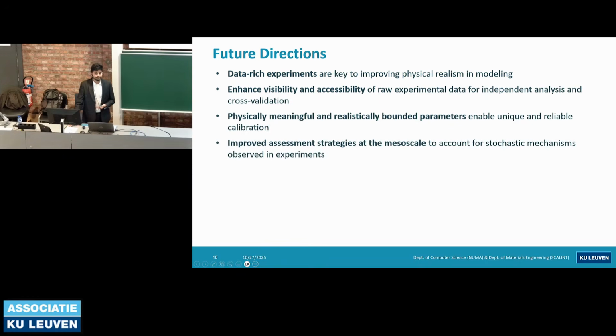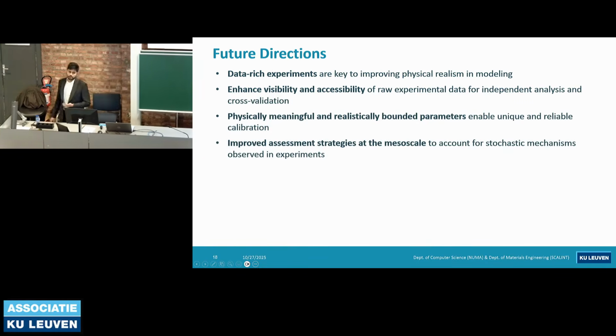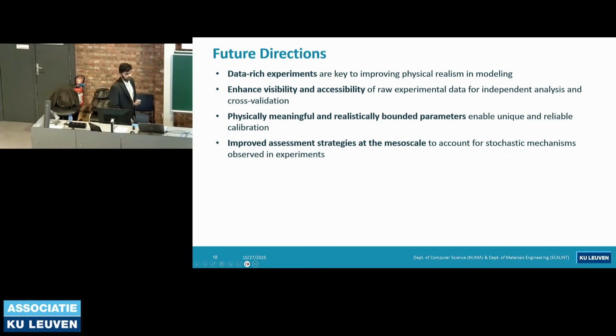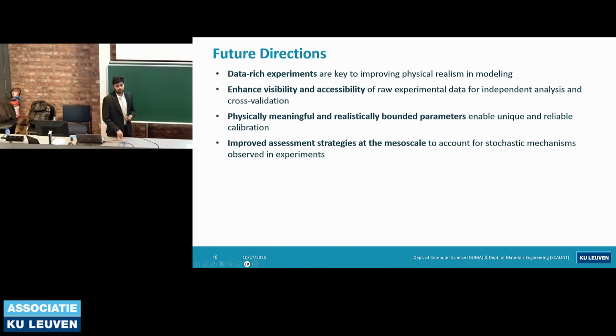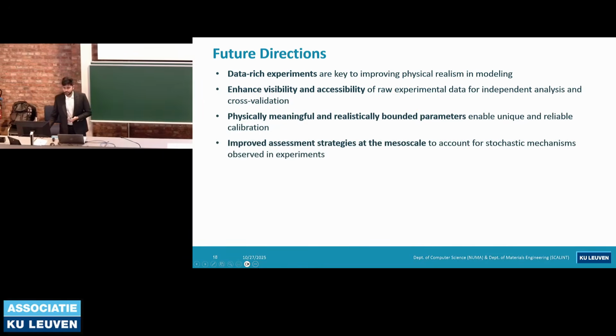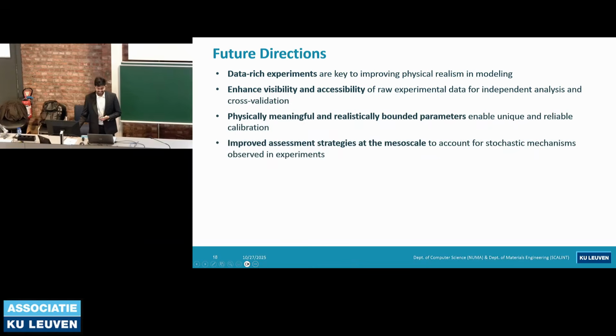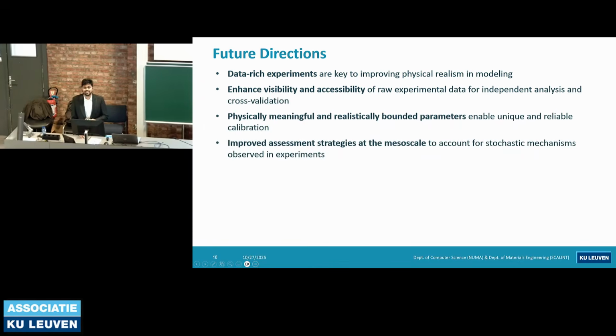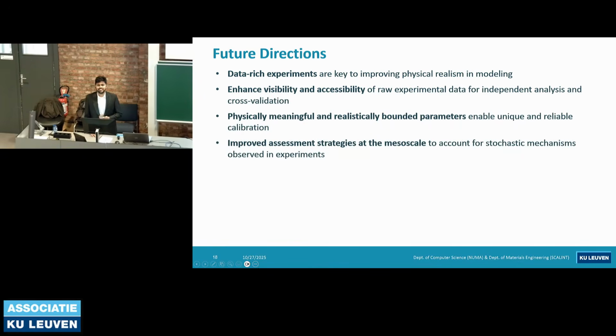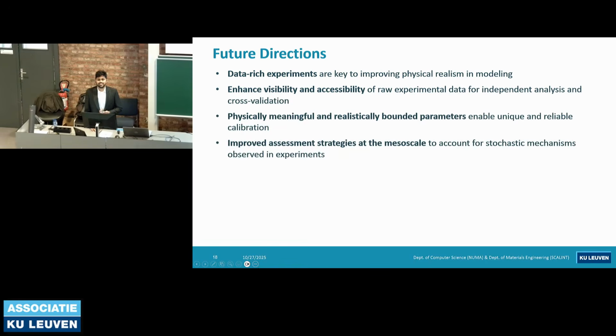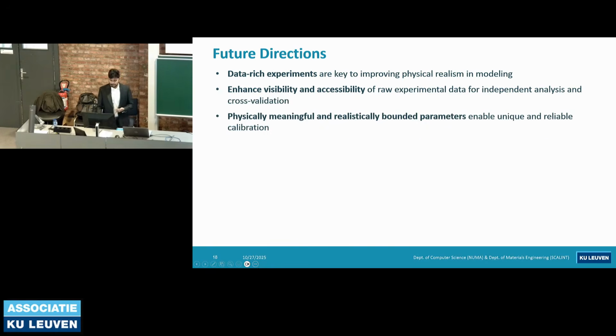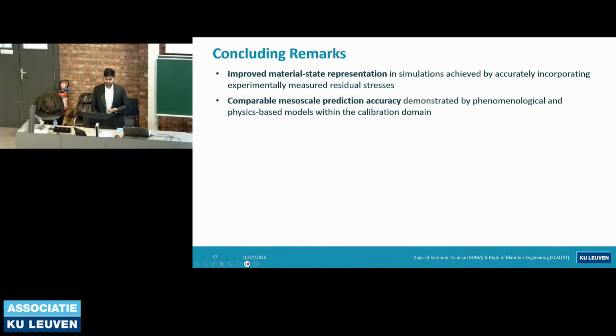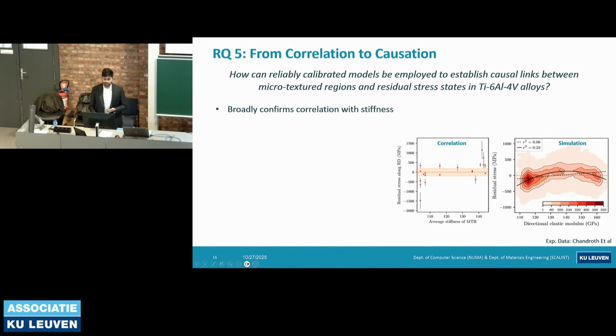Well, thank you for the presentation. It was really clear. You had a presentation of the residual stress data, and there were only a few grains. But then for the simulations, did you use only those 20 grains, or was there a representation for the rest of the microstructure? No, for simulations, I used all the grains, but the residual stresses were only incorporated in these grains.